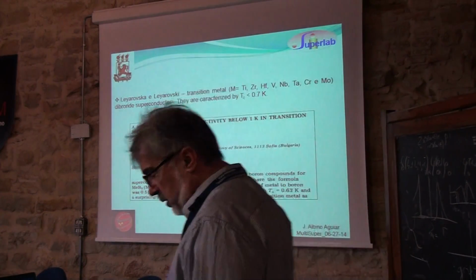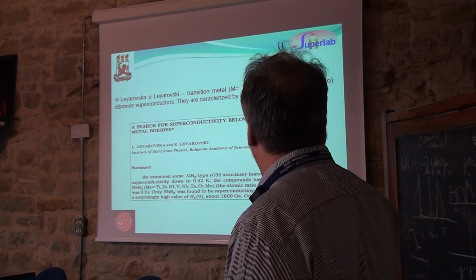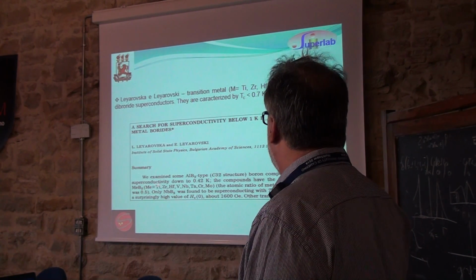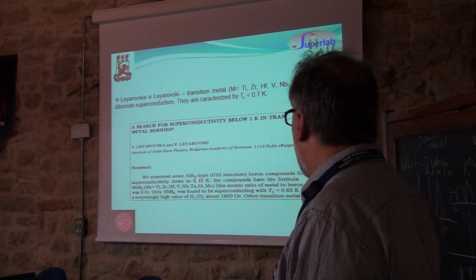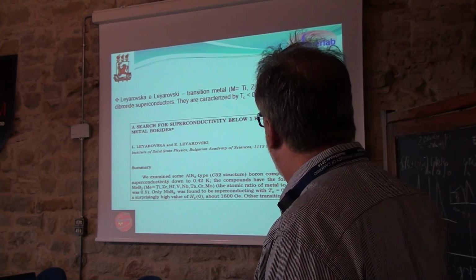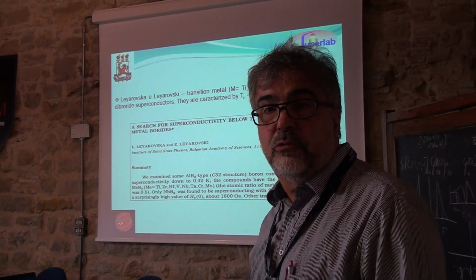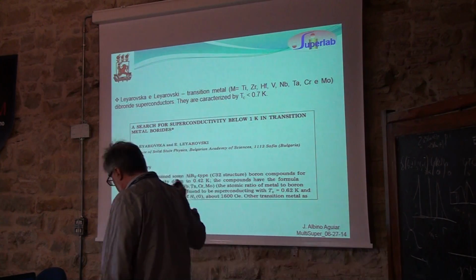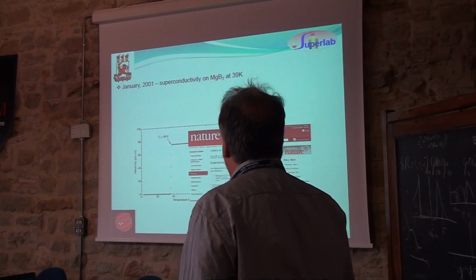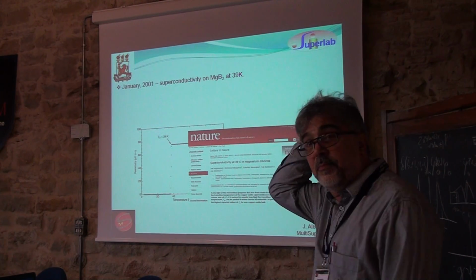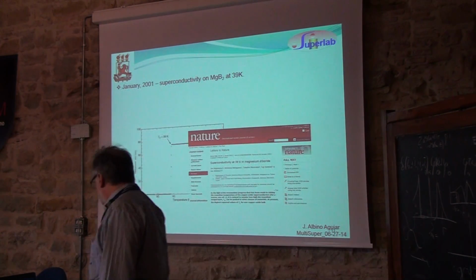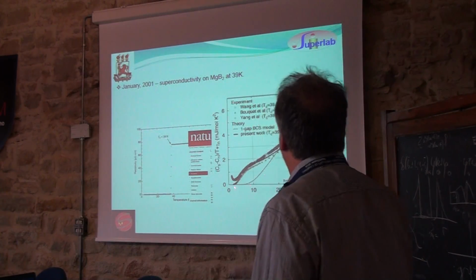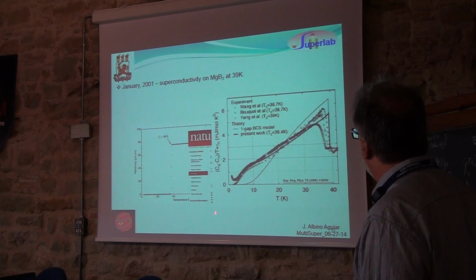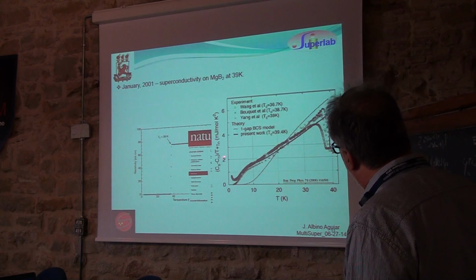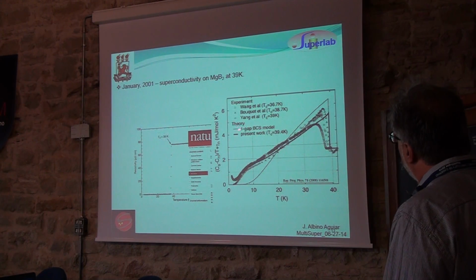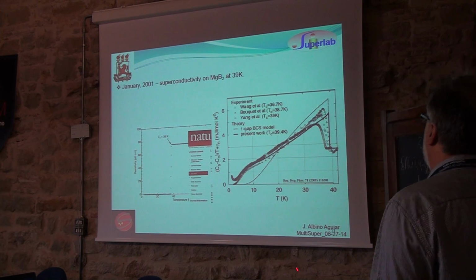These people, Leyarovska and Leyarovski, studied all these compounds: metal boron 2 with titanium, zirconium, hafnium, vanadium, niobium, tantalum, chromium, and molybdenum. And they found superconductivity only for niobium boron 2 at a very, very low temperature. Then we had Akimitsu's discovery of superconductivity in magnesium diboride, and it was shown that it has two gaps. For example, I chose this result where you have the heat capacity compared with a one-gap model theory and two gaps, and you see that it fits.